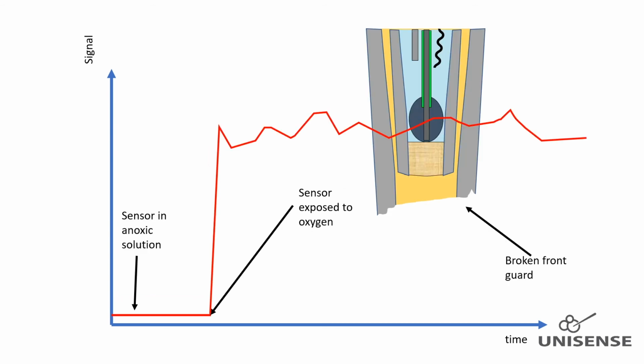If only the front guard glass casing and membrane are damaged, it might still be responsive to nitrous oxide, but will be sensitive to oxygen. Oxygen interferes strongly, and thus a large signal will be generated in oxygen-containing samples or in air. If the signal is low and stable in anoxic samples close to the baseline, but unstable and high exposed to oxygen, the outer glass casing, glass or membrane is most likely damaged. It is not possible to repair a broken sensor or replace the outer casing.